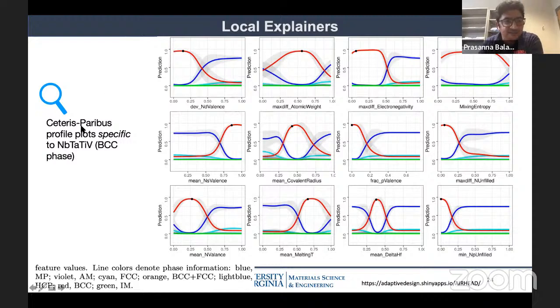This is called a Ceteris Paribus plot, a profile plot. This is also a plot specific to, for example, the niobium, tantalum, titanium, vanadium example, right? So here, every black dot that you see is the value that corresponds to this particular niobium, tantalum, titanium, vanadium alloy as a function of different features. And the continuous lines that you see here essentially indicate what the model thinks. This behavior of this alloy will change if you keep everything else constant and change only one of the variables here, right? So this is a busy slide.